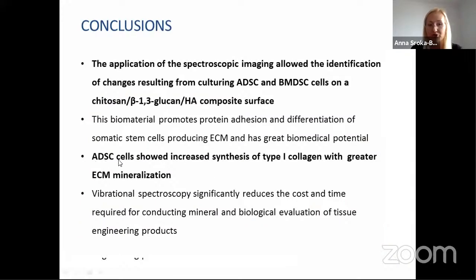And also we showed that ADSCs showed increased synthesis of type 1 collagen, which was the higher extracellular matrix mineralization. And those three spectroscopic techniques were very useful for analysis of these materials.